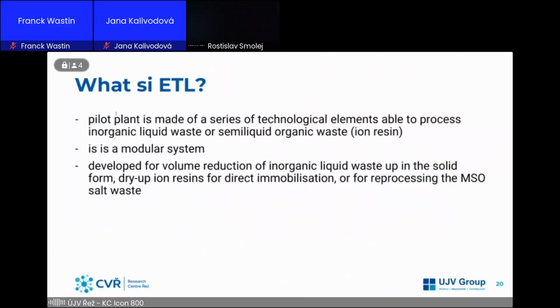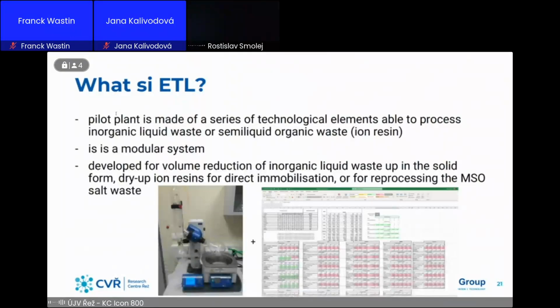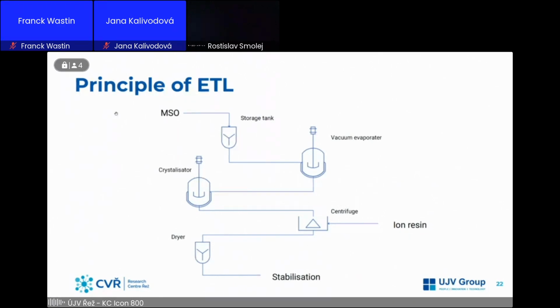It needs to be really prepared for this process, so that means that there's lots of work in the lab, that's the left-hand side, and then behind the desk, because you need to really prepare for the process to know how much water you can evaporate from the system to oversaturate it a little bit, but not that much. Yeah, it's a really time-consuming process. In principle, the ETL looks like this. You have the molten salt oxidation at the beginning, then you have the storage tank, vacuum evaporator. From that it goes to the crystallizer, up to the centrifuge, the ion resins mainly going to the centrifuge, and then the dryer, and in the end we have the stabilization.